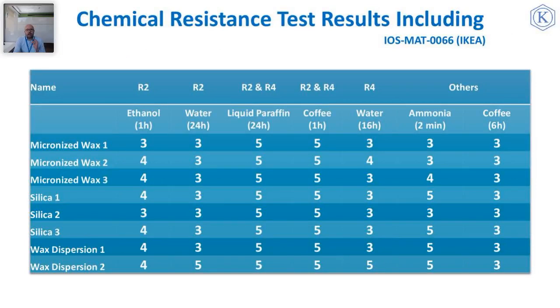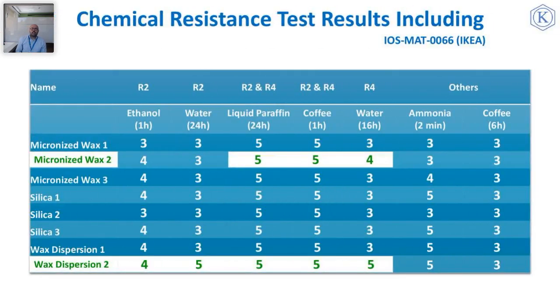In matting systems, IKEA chemical resistance requirements were also checked, and assessments for R2 and R4 performance were made. According to IKEA norm IOS MAT 0066, on a 0 to 5 scale, 4 is an acceptable result for chemical resistance. It is well known that meeting R2 requirements is a tough target to achieve with self-cross-linking acrylics. However, when we look at our results, we see a surprising result with wax dispersion 2, which achieves R2 requirements. All the other matting agents fail for R2 because of 24 hours of water resistance.